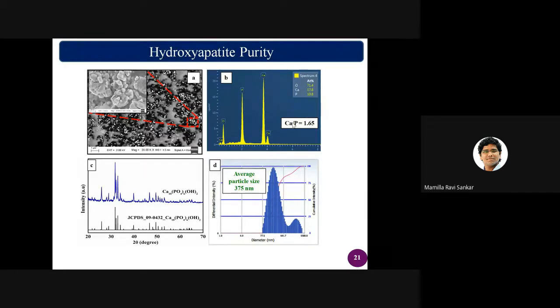More than that, you can go for XRD analysis of your powder, and at the same time you have a library called JCPDS. Once you superimpose the JCPDS data with respect to your data, you can measure in terms of two techniques. One is the peak intensity method, another one is Rietveld analysis. If you are in a hurry, you can go for the peak intensity method and check. Otherwise, if you have time, it normally takes 2-3 days. If you are not familiar, you can do Rietveld analysis and measure.